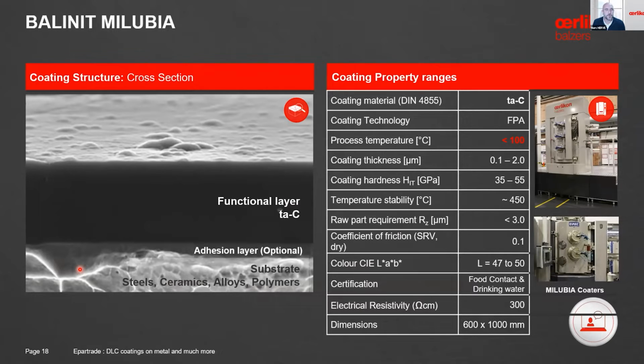And if you want to coat elastomer, that might be an issue. One of the key points of the Milubia coating is that it is made at very low temperature. It's actually made below 100 degrees C. We even measured coating around 80 degrees C. So, non-conductive substrate, very low temperature, and we can do from a few nanometers to a couple of micrometers.